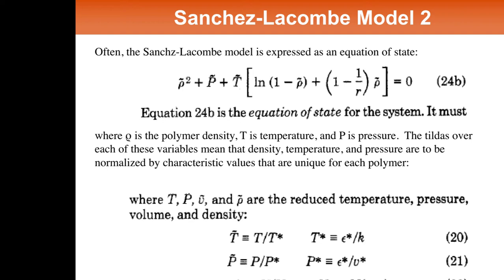And he fixed it by extending the Flory-Huggins model to include vacancies in the lattice that's used to model the thermodynamics of such systems. And having the vacancies there introduced the possibility that those vacancies could be removed with temperature or with pressure, and the material could be compressible. And it resulted in an equation of state that's shown here. We've gone over this previously. I won't belabor it, and it gave essentially for the first time a fundamental model to predict, for example, density versus temperature for a wide variety of polymers and as a function of pressure.